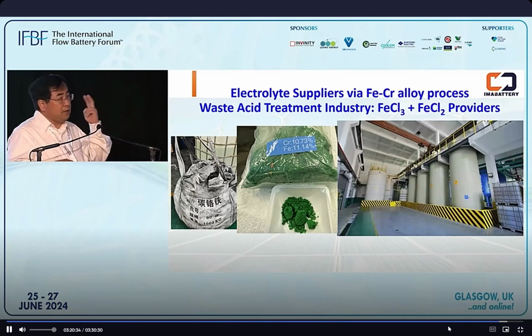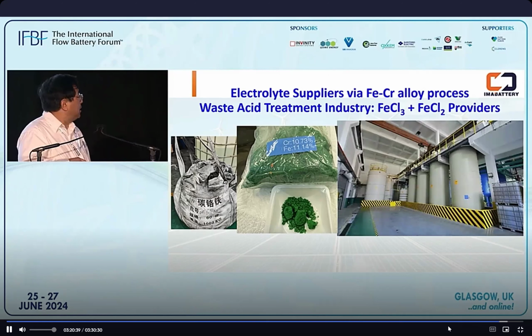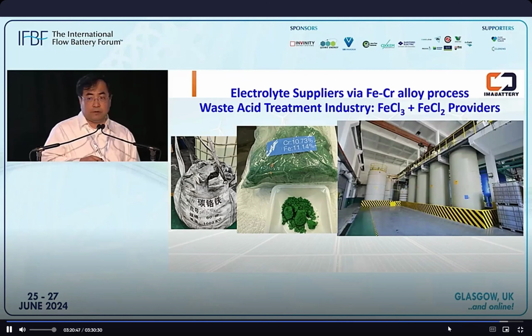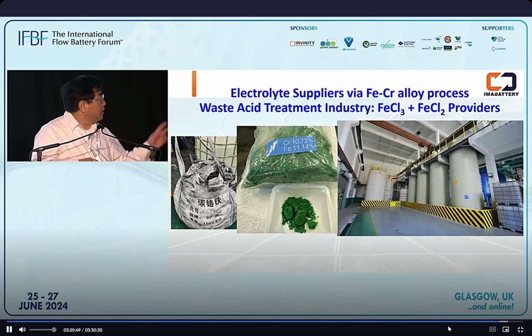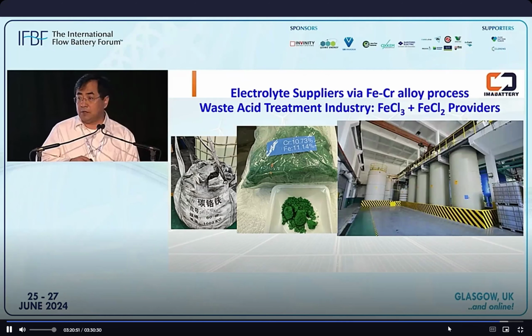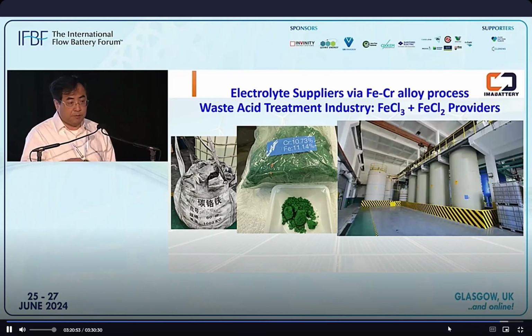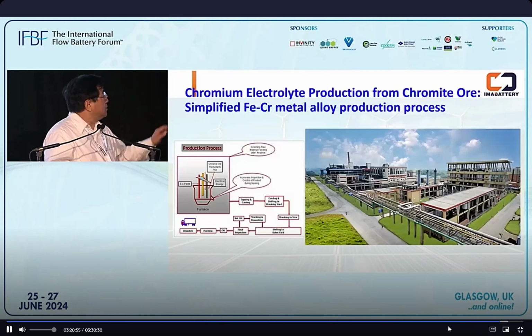So we identified 2 vendors already, and they use this iron chrome alloy metal and produce the electrolyte here, and also produce the mixed crystals. Each of them has a gigawatt hour electrolyte production capacity per year. So this is one good thing.